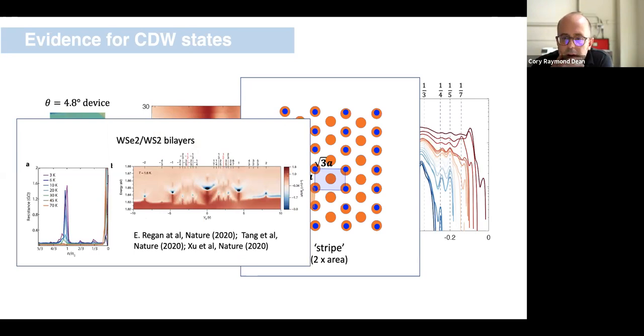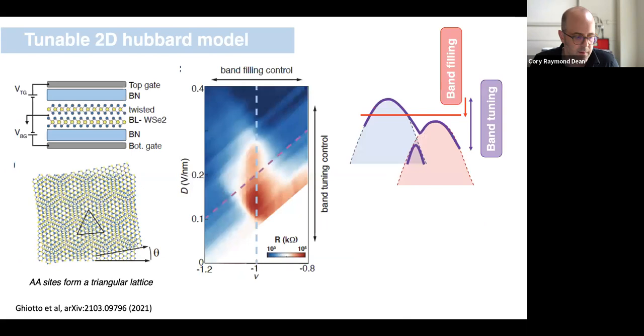So this is work by Jie Shan's group at Cornell, and also Feng Wang's group at Berkeley. In the heterobilayers, they found that indeed there's sort of ubiquitous evidence of there being charge density wave states in these systems. So we think that's likely what's going on here, but we haven't yet gone back and studied these in detail.